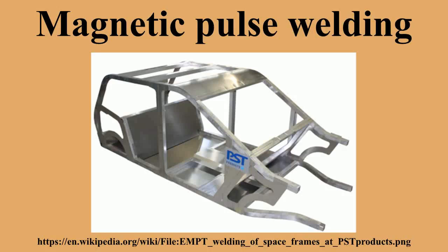Jetting condition. The collision has to be supersonic compared to the local material speed of sound to generate a jet. High pressure regime. The impact velocity has to be sufficient to obtain a hydrodynamic regime, otherwise the parts will only be crimped or formed. No fusion during the collision. If the pressure is too high, the materials can locally melt and re-solidify. This can cause a weak weld.